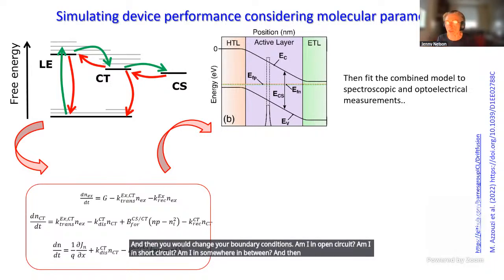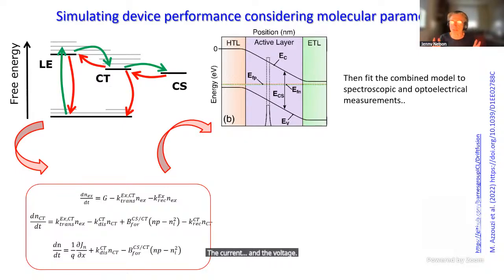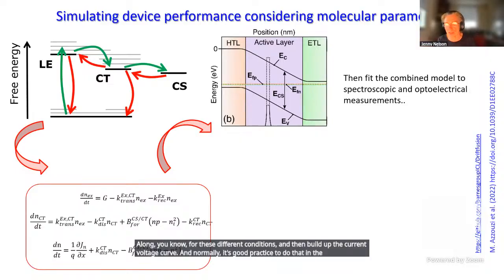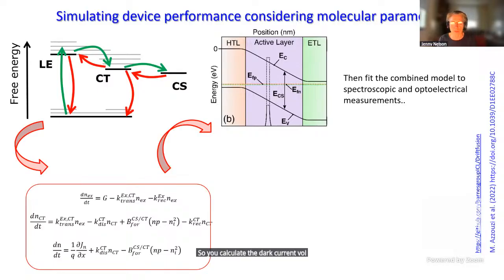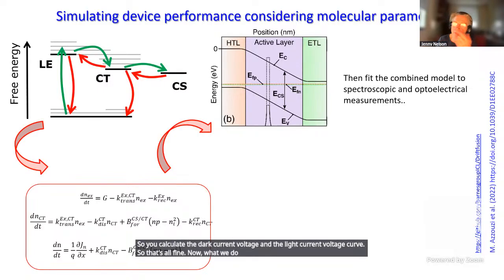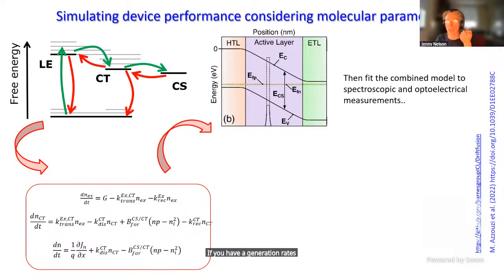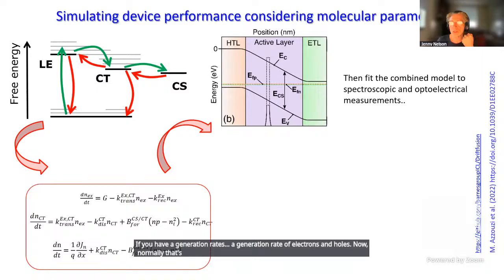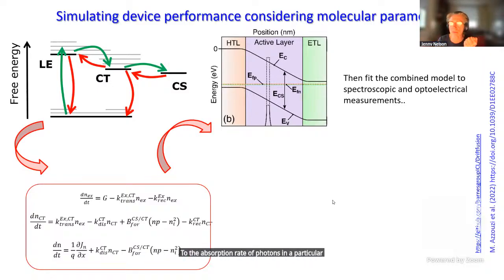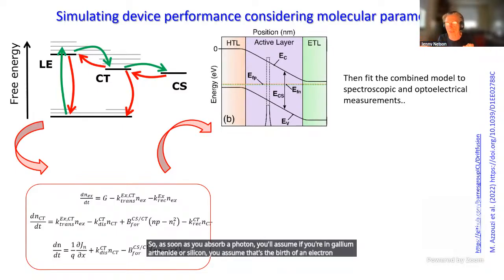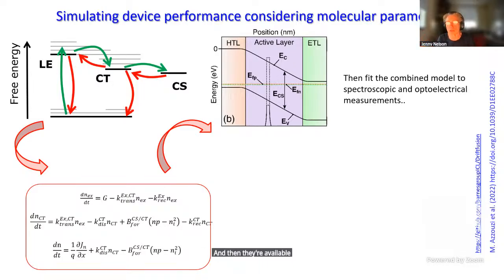Then calculate the current and the voltage for these different conditions, and then build up the current voltage curve. Normally it's good practice to do that in the light and the dark, so you calculate the dark current voltage and the light current voltage curve. Now, in such a model, normally the assumption is that the generation rate of electrons and holes is identical to the absorption rate of photons in a particular element of space. As soon as you absorb a photon, if you're in gallium arsenide or silicon, you assume that's the birth of an electron and a hole at that place together, and then they're available to contribute to the current.